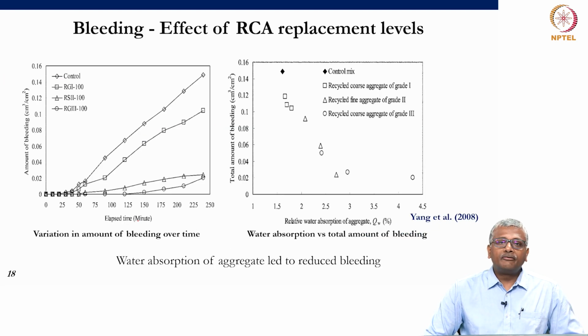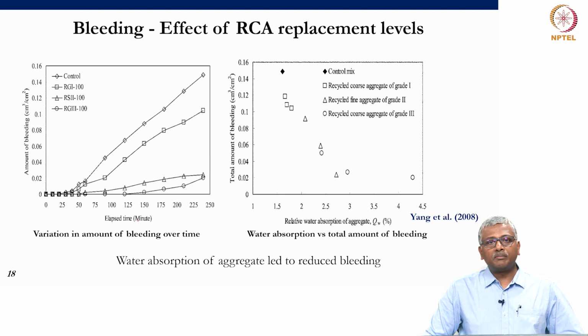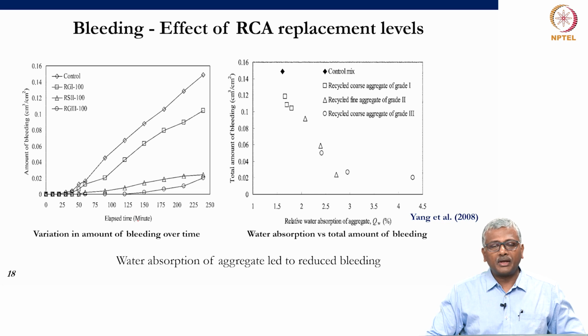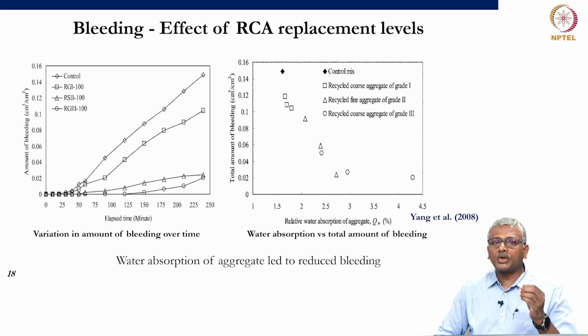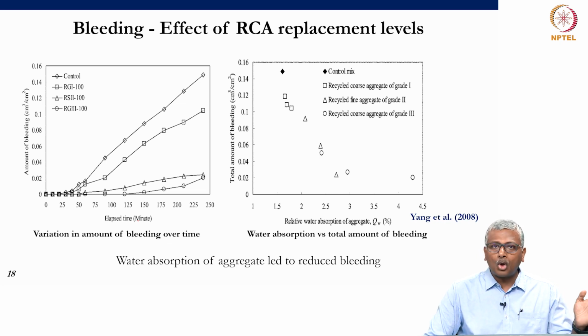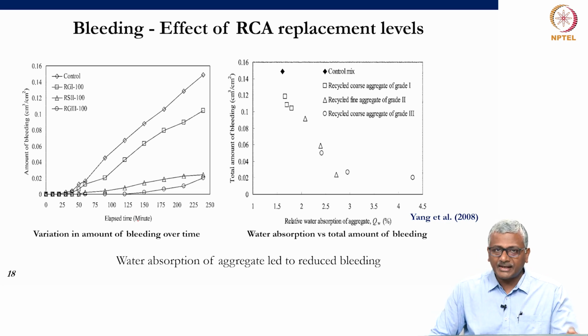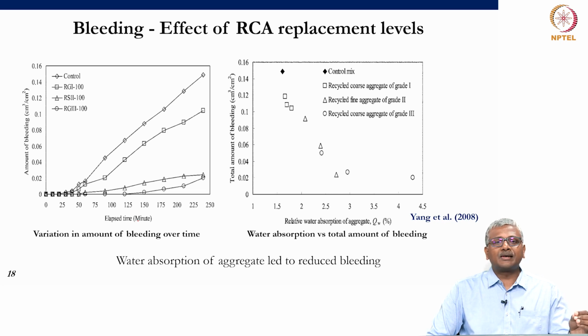Now, when it comes to bleeding, we know that bleeding happens when there is a lot of free water that tends to rise up to the surface. Okay, what will happen when recycled concrete aggregate is there? If this recycled concrete aggregate has adhered mortar, it will tend to also absorb the bleed water. So, as a result, what you can expect is when normal aggregate is replaced by recycled concrete aggregate, you should see some level of reduction in bleeding.